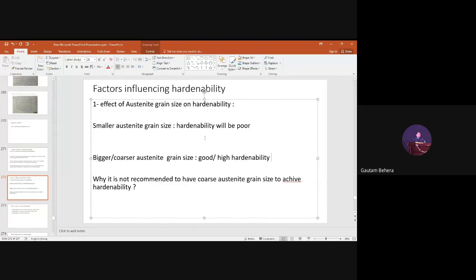So why is this so? If we have small austenite grains, that means we have a lot of grain boundaries, right? And if we have a lot of grain boundaries, we have a lot of easy diffusion paths. Diffusion will be easier, and pearlitic transformation is a completely diffusion-based transformation. If diffusion is easy, then pearlite formation will be easy. That means nucleation and growth of pearlite will be easier. So if we have smaller austenite grain size, we have many grain boundaries, which means easy diffusion paths, and the rate of nucleation and growth of pearlite will be faster. So austenite will easily transform into pearlite, which suppresses the formation of martensite.